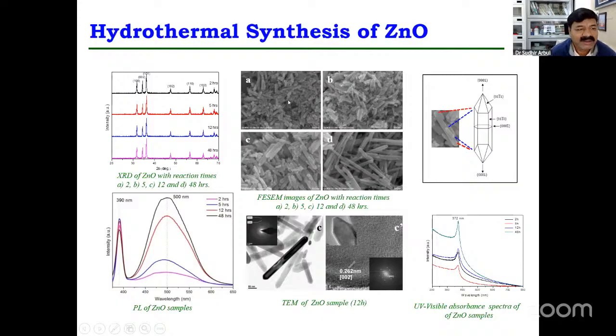See what happened. In SEM, we see that the length of the rods is a few nanometers. As we increase from 2 hours to 5 hours, it is up to a few hundred nanometers. Then it is 500 nanometer. And at 48 hours, the length of the rod becomes micron size.